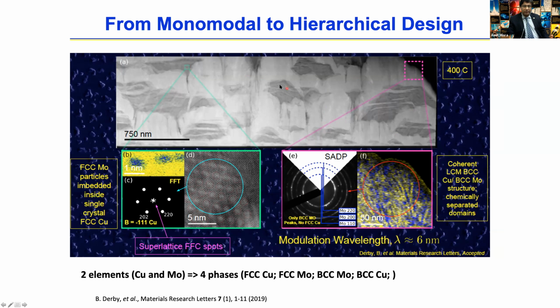In the matrix are these discontinuous islands, these darker looking regions shown by the green box and blown up here. Those darker regions are copper rich. Copper is lighter than moly, so it appears darker, but it's not pure copper. If you blow it up, the yellow matrix is the copper and the blue regions are moly rich. So those copper rich islands actually contain a superlattice of moly rich precipitates, which leads to these diffraction spots that account for the periodicity of those superlattice precipitates.